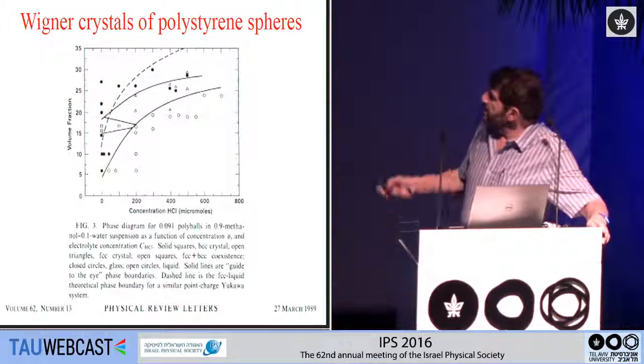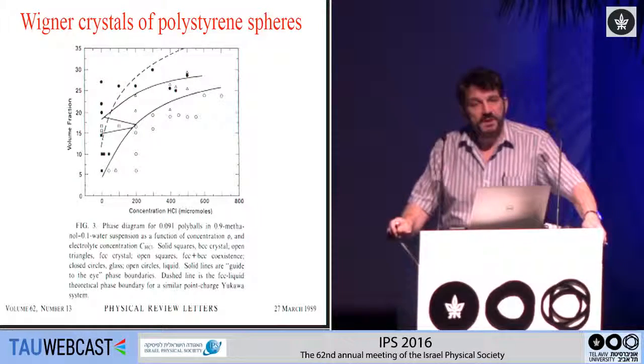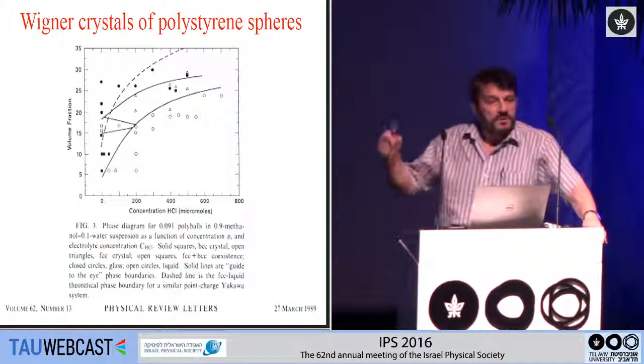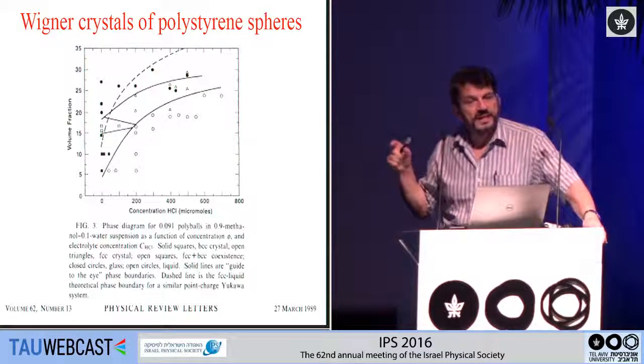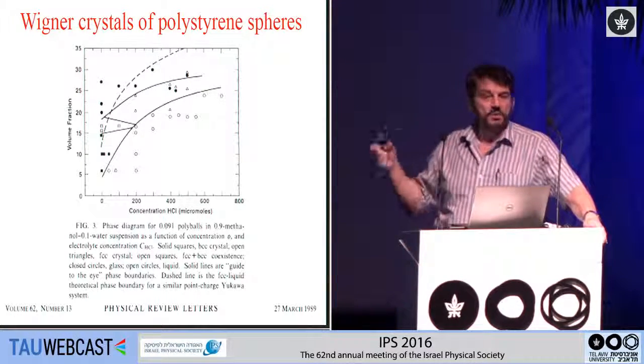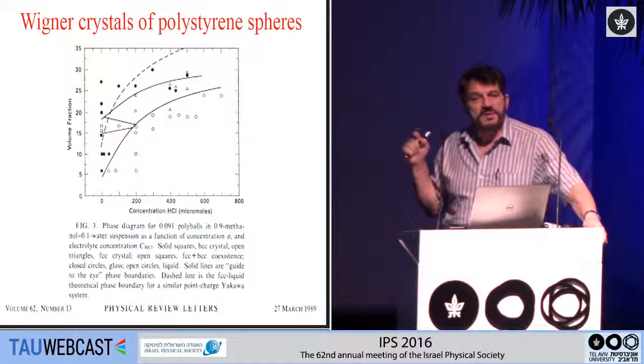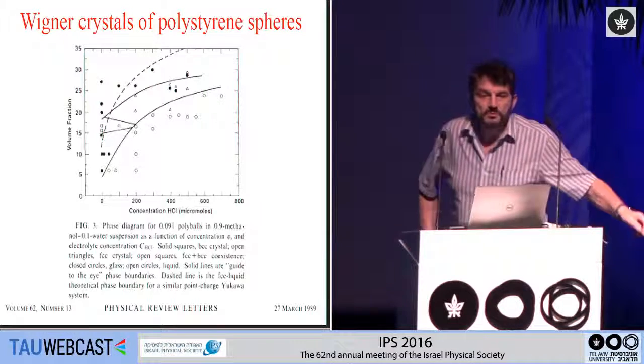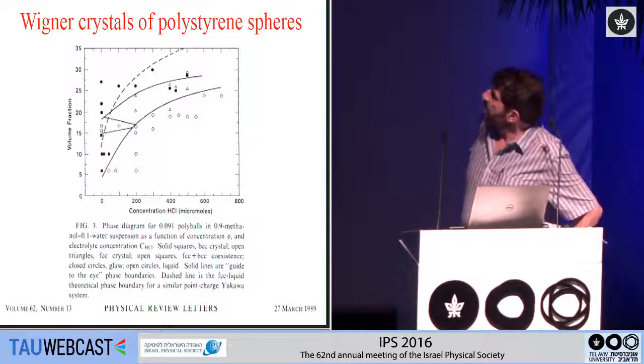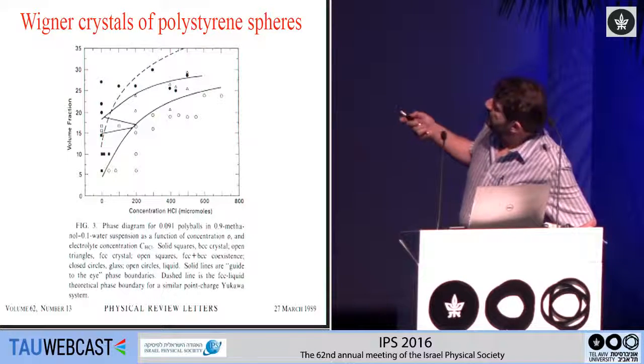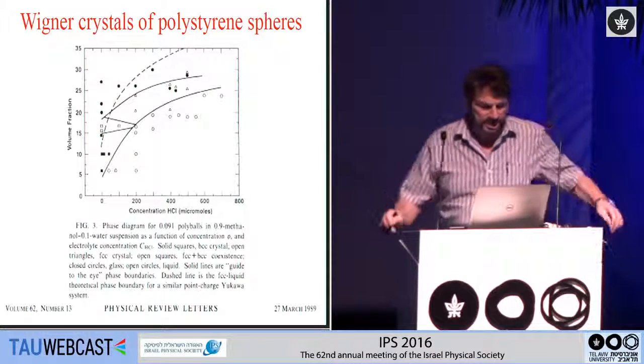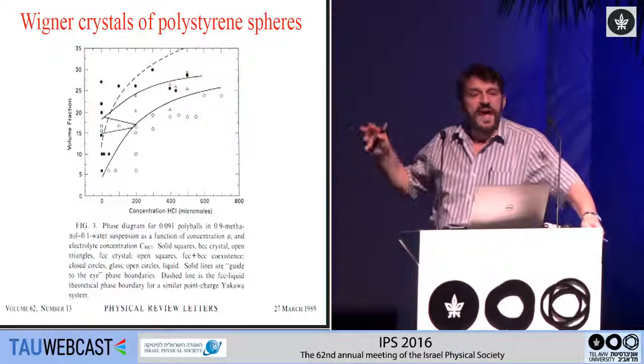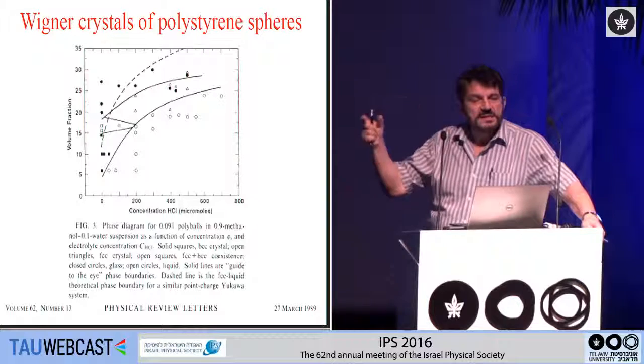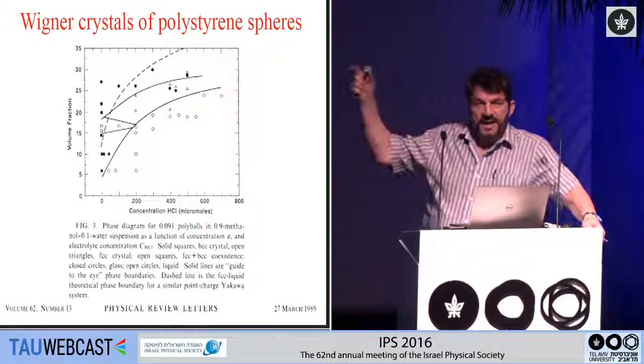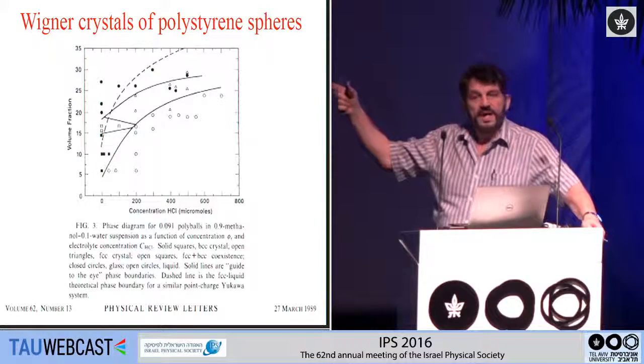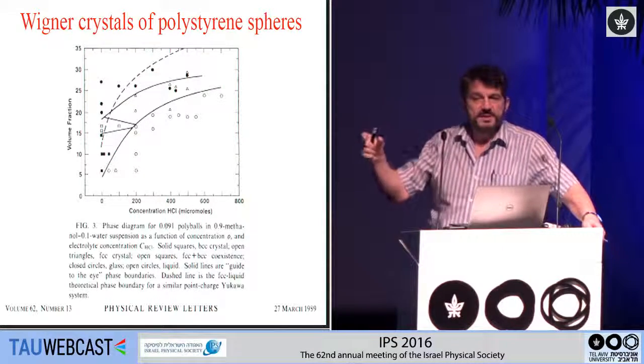And these experiments were done with 91 nanometer polystyrene spheres in water. You can't really see through them, so they used X-ray scattering. The length scales are relatively short. They're sub-micron length scales. And so X-ray scattering was the only way that they could resolve the behavior. And they saw a classic, standard kind of behavior where as the system melted, it went from an FCC lattice, face-centered cubic lattice, at high concentrations to a BCC lattice near where it melts.